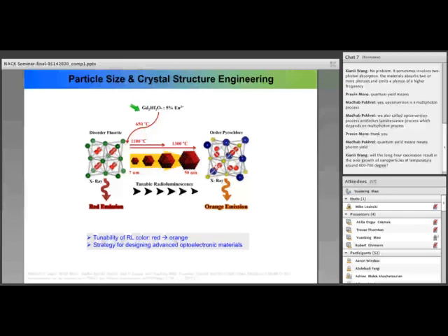So here, what I want to show you is we start with this composition, gadolinium hafnium, doped with 5% europium 3+. Again, we use the europium as the optical probe here. One important thing I want to mention is that with the molten salt synthesis process we developed, we synthesize this type of nanoparticles at 650 degrees Celsius, so it has a disordered fluorite structure. That's one thing I mentioned to you: we can synthesize this type of metastable phase at this temperature.